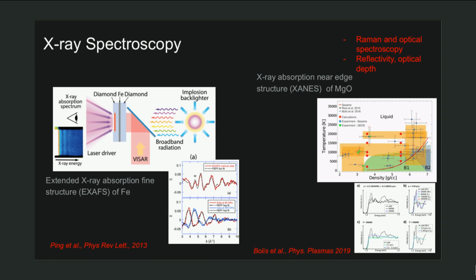We look at the reflectivity of the shock front, and that can be correlated to, for example, the metallicity or the emissivity of a material. And so combining the emitted or the reflectivity properties with in situ probes like X-ray diffraction allows us to really leverage all those different techniques together.